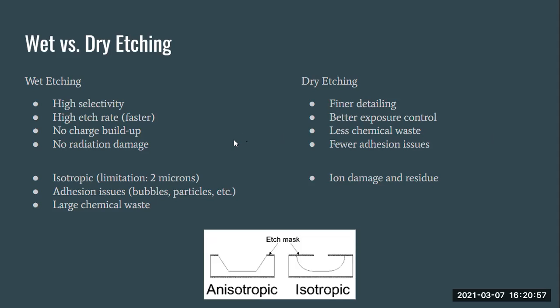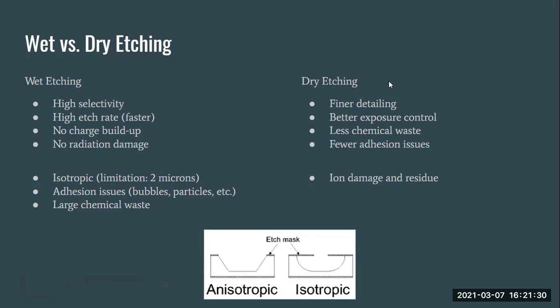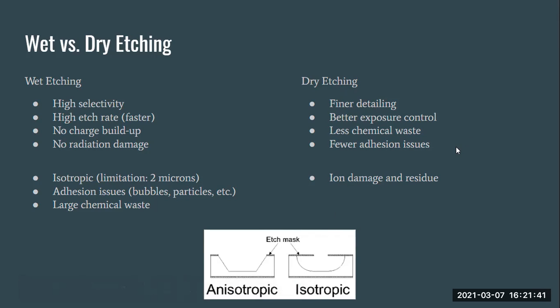With wet etching, the main thing to take away is that you get this effect down here in the right side of the image. This is for an isotropic removal. And so what you see is that while this mask is here, when the etchant is removing material, it digs underneath the mask a little bit. And that's a reason why dry etching would be preferred and why it can be used for smaller details. Wet etching is limited by 2 microns before it starts to become a major issue here. And so if you want something smaller than 2 microns, you're going to have to start working with this dry etching process. And that gives us a cut that looks a lot more like this one on the left.